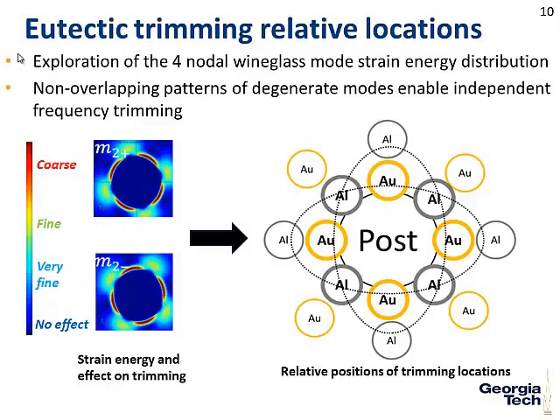So in the slide before, I told you that gold has the capability, when you do a gold silicon eutectic, to increase your frequency. So if you were to use the low frequency and to use gold, you would need to melt the gold at this location, and at this location, and at this one, as I'm showing here, to be able to bring the low frequency mode to the high frequency mode. But if you were to put aluminum on the bottom of your device, then you actually have to use this pattern. So our technique can shift frequencies upwards and downwards, but we can only do it in one direction for one given metal. So if we use aluminum, it has to go downward. So the relative positions of the trimming are different for aluminum and for gold.